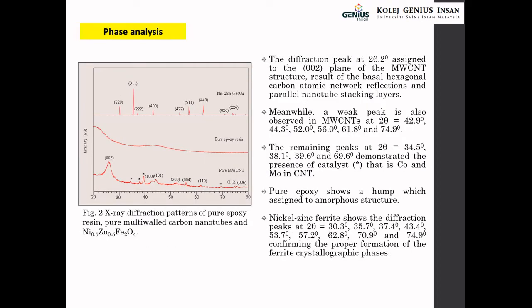Phase analysis by using X-ray diffractometer. This is for pure multi-wall carbon nanotube, pure epoxy resin, and nickel zinc ferrite. You see that for pure MWCNT, the 002 plane is the main peak, and there are also remaining weak multi-wall carbon nanotube peaks. The remaining peaks demonstrate the presence of catalyst, that is Co and Mo. For pure epoxy resin, there is a slight hump here, which is assigned to an amorphous structure. And this is the nickel zinc ferrite plane, which shows proper formation of the ferrite crystallographic phases.